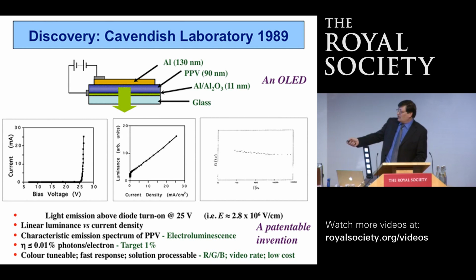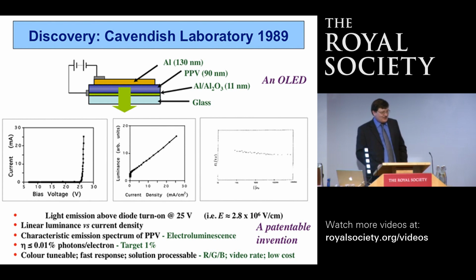And if you work out, was this a good dielectric? It actually was, because 3 megavolts per centimeter is the point at which this voltage actually starts to inject charges. So if it hadn't been a good sample in terms of its dielectric properties, it would not have been possible to inject charge into that structure. We see a nice linear luminance-current relationship, and the emission spectrum is characteristic of the polymer, so we can show that it's electroluminescence. The efficiency of these devices, 0.01% photons per electron. That's not a lot of photons per electron. It certainly wouldn't excite you in terms of making a device.